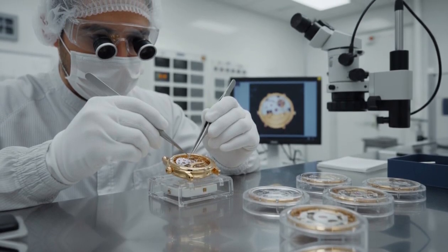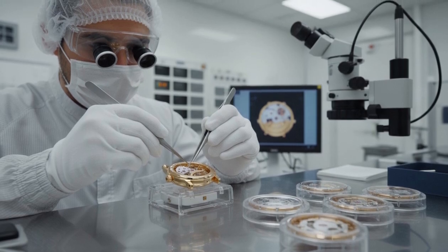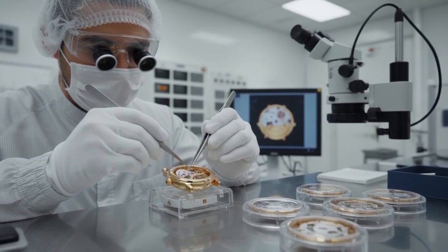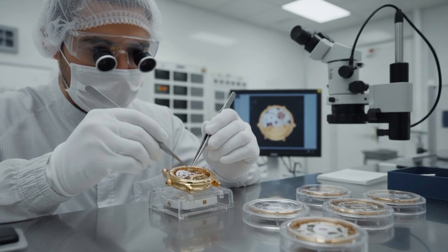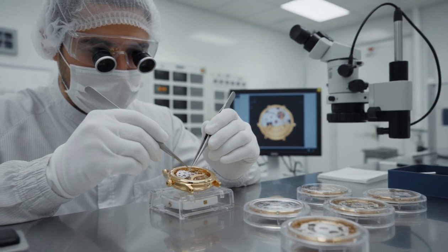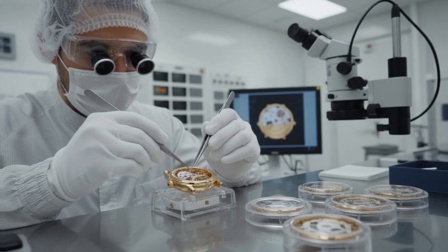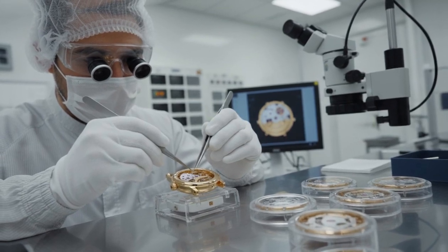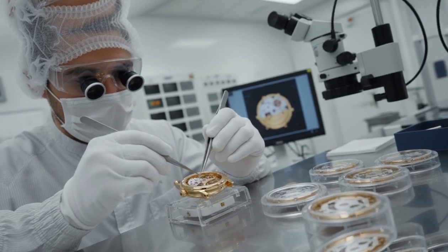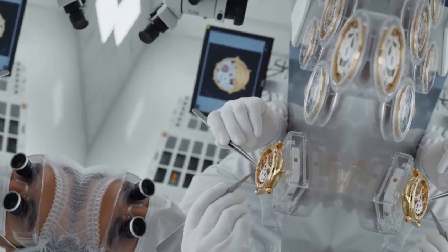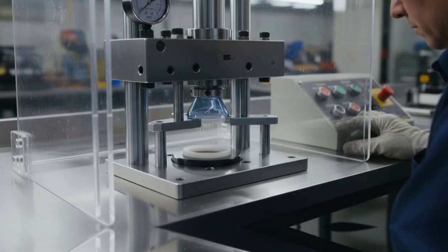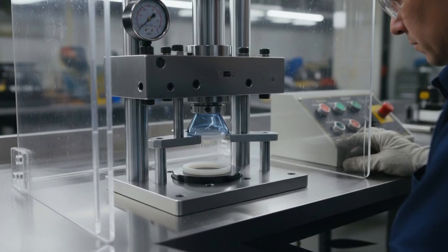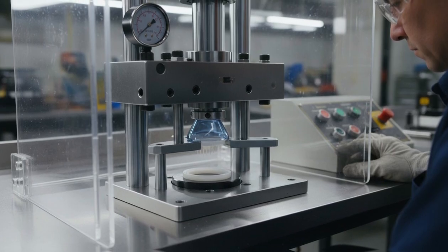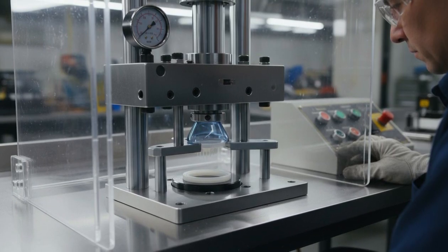After all, the difference between 74.9% and 75% gold is barely measurable and wouldn't be noticeable to anyone wearing the watch. But Rolex doesn't build watches to barely acceptable standards. They build to the standards they've set for themselves, and those standards have no tolerance for close enough. Beyond chemical composition, the bars undergo testing for mechanical properties. Small samples are subjected to tensile testing to measure strength and ductility, hardness testing using diamond tip probes, and microscopic examination to verify grain structure. Only after passing every test does the alloy receive approval for use in watch production.